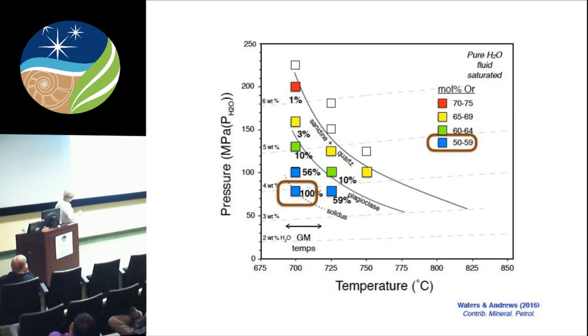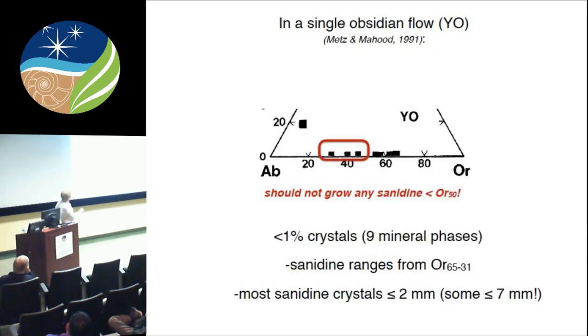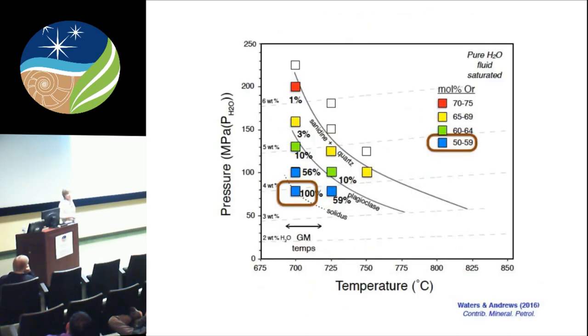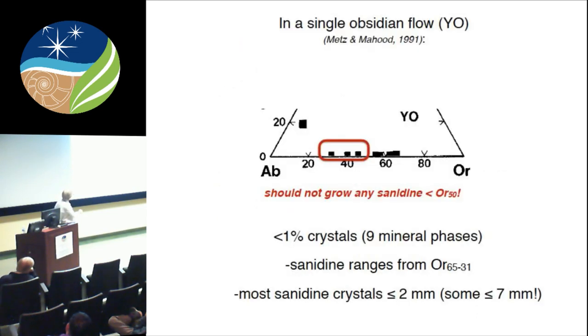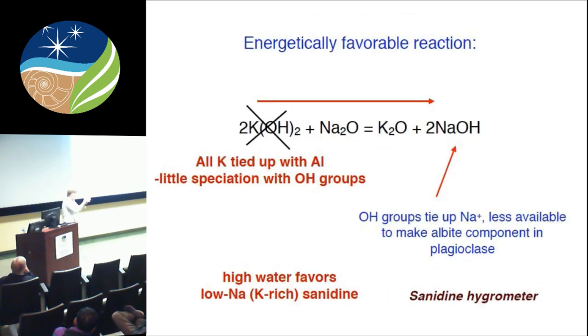And so you can see that here at the solidus, she doesn't see anything more orthoclase poor than orthoclase 50. But remember, we see things going all the way down to 31. So we shouldn't be growing anything more orthoclase poor than 50. So how do we get down to 31? Well, first of all, we think that what's changing the composition of the sanidine in the Glass Mountain is that hydroxyl groups preferentially speciate with sodium relative to potassium. And the only reason is because potassium is so busy with aluminum. And I'm going to show you phase diagram results that demonstrate this effect. So this is our hypothesis.